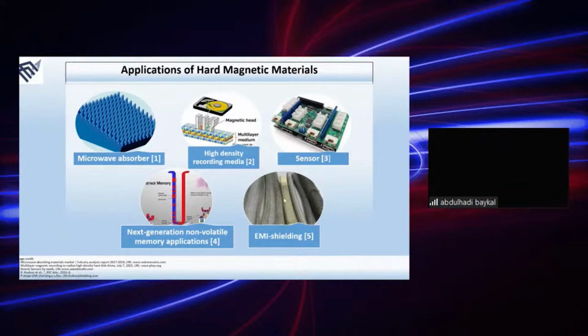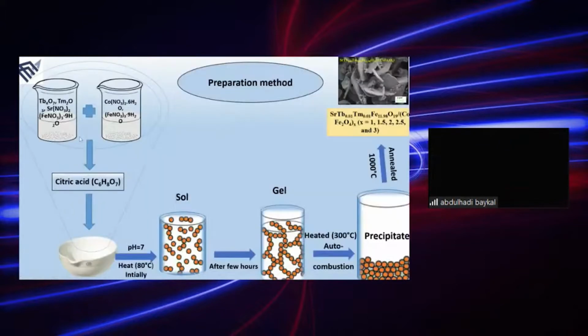So it means that you know that our nanocomposite consists of both hard and soft parts. For the hard part, we mix them together, okay. Then of course the liquid, a minimum amount of water, both of them, okay. Of course we will also dissolve citric acid in a minimum amount of water after blending all of them in a mortar. Then we will adjust the pH of the solution to 7, and we will heat it up to 80 degrees, and in that case it is still a solution.